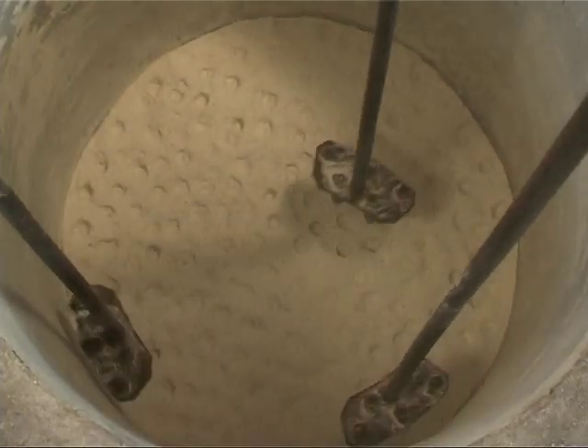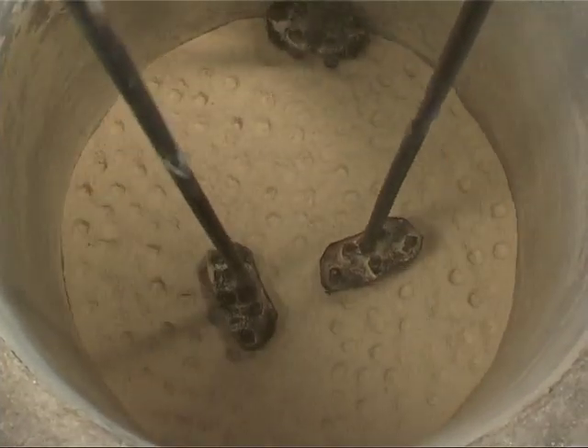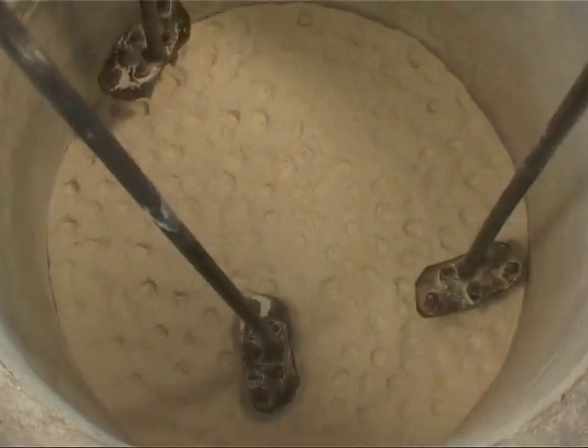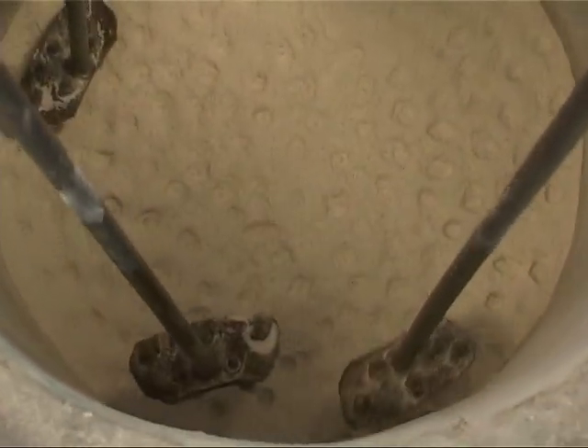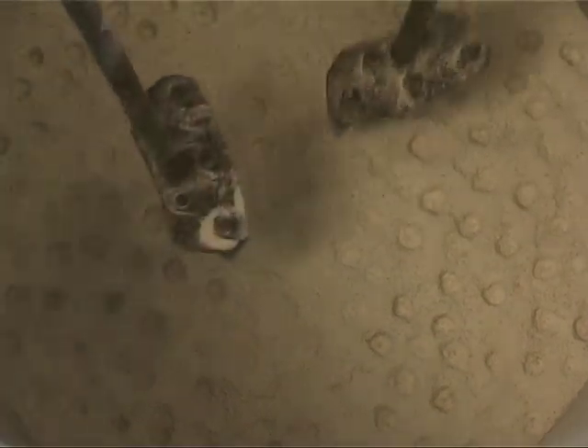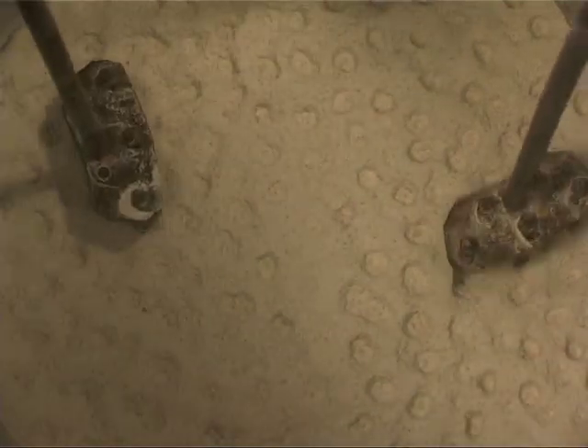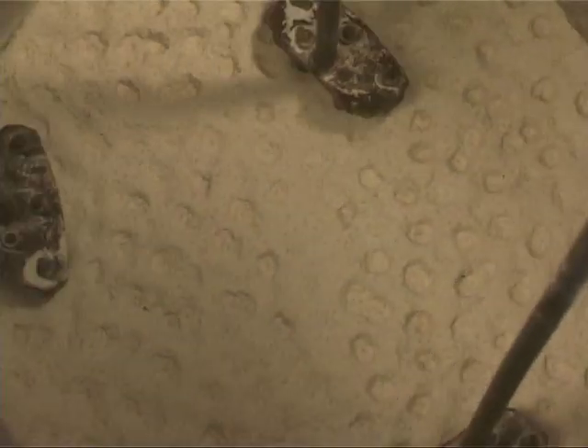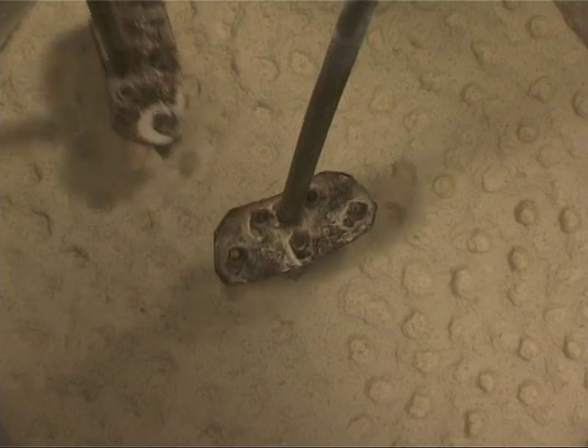ram the bottom lining at the rate of about 40 man-minutes per square meter. This allows entrapped air to escape and finer particles settle into the spaces between larger ones to give a compact lining. Add further ramming mix in 50 to 60 mm layers and fork ram again.